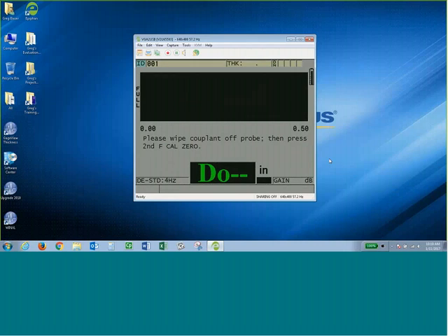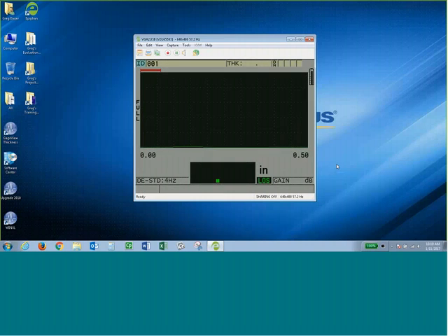This is that auto zero feature, so it's nice to get this help text. Please wipe couplant off probe, then press second F, cal 0. Second F, cal 0. The gauge measures the time through each of those delay lines. I'm going to be measuring on a 4-step test block from 1.5 inches, then the next step is 0.75 inches, then 0.3 inches, and then 0.15 inches. Change my range so we can see the signal on screen.